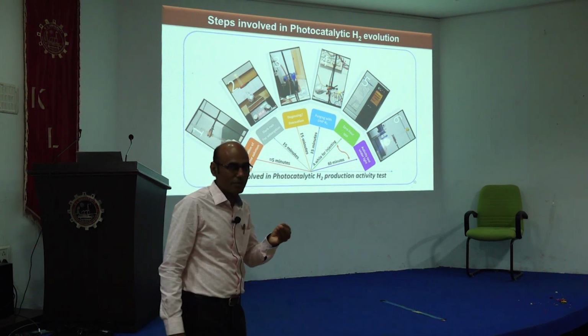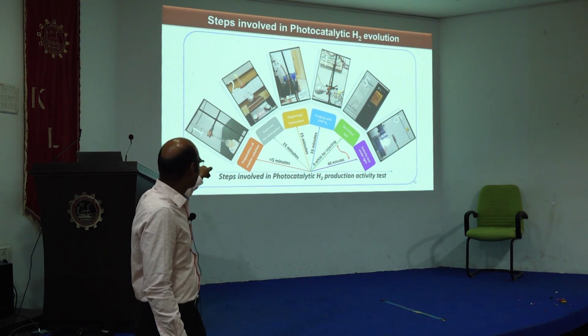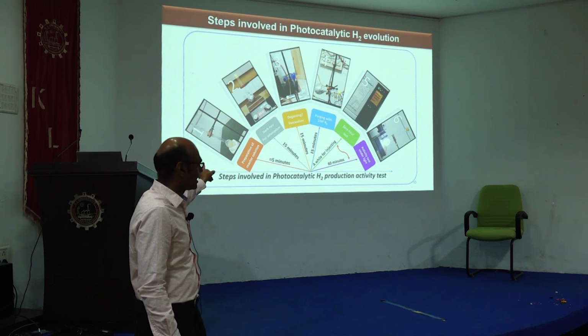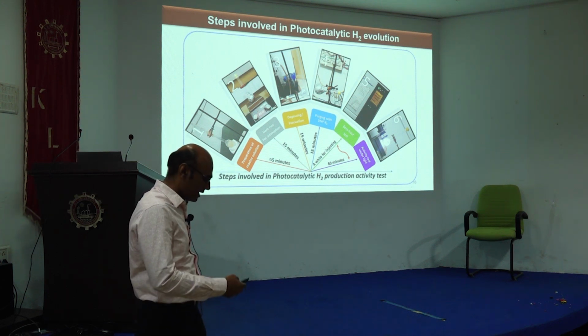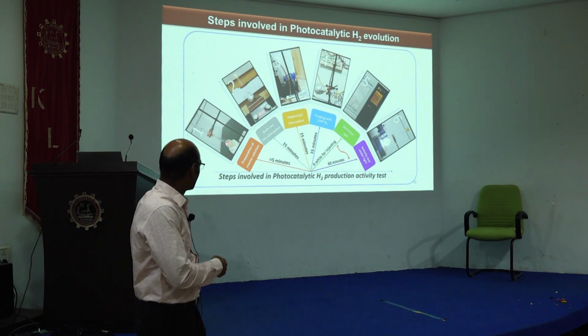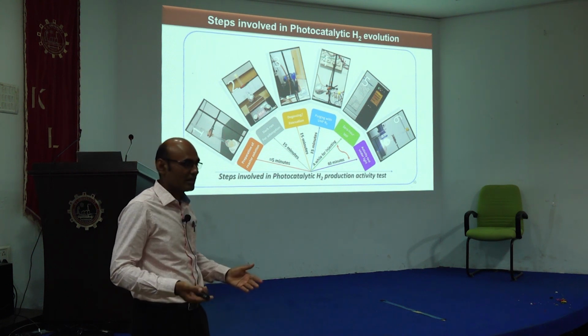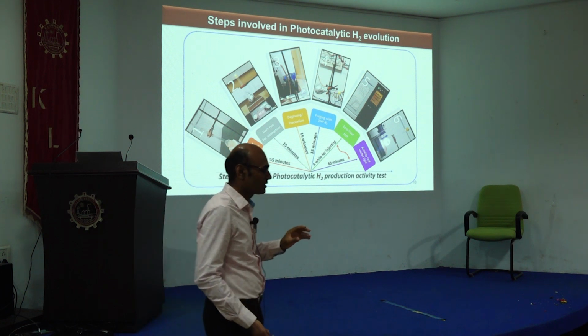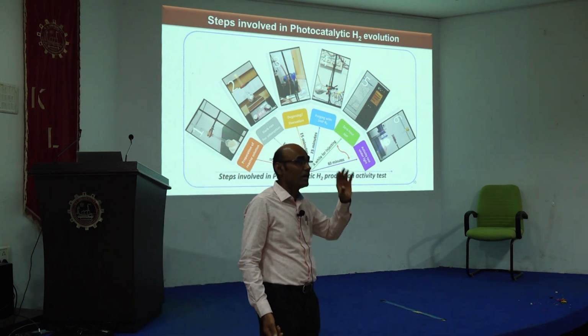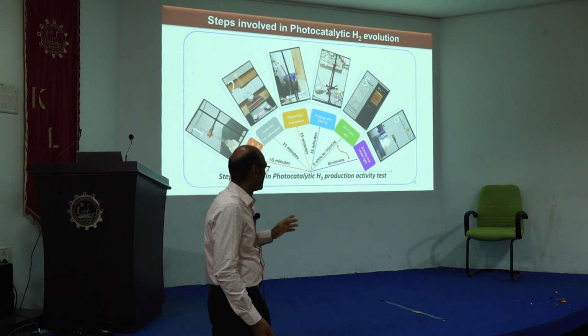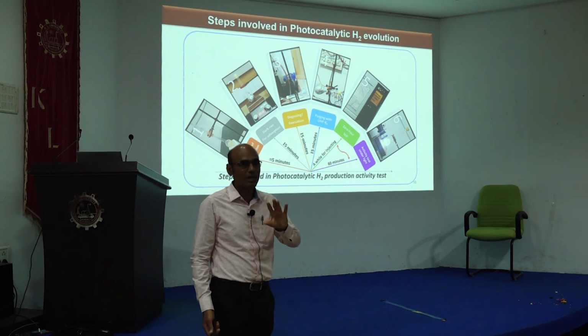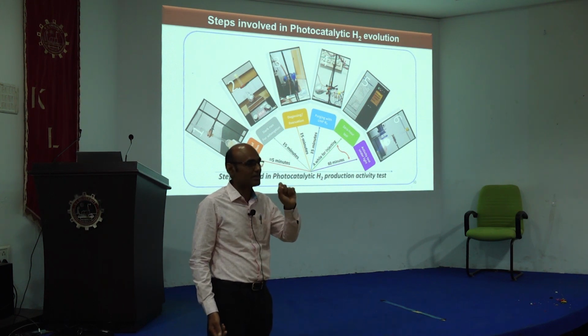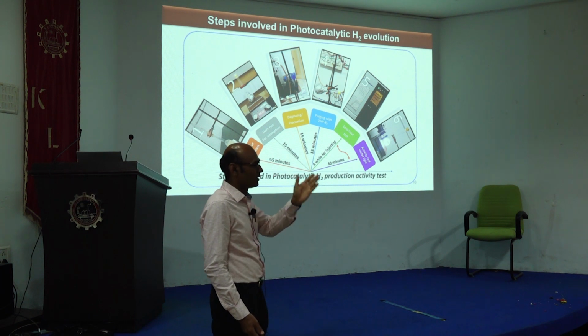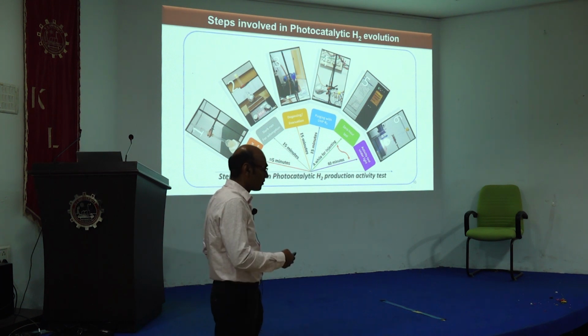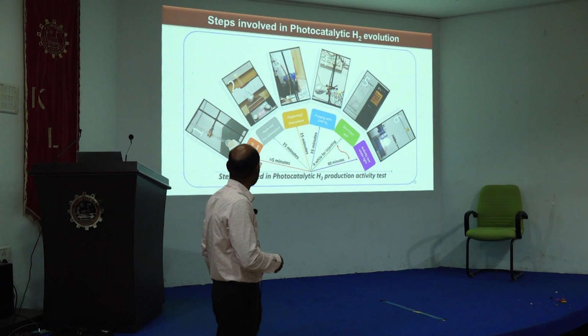First, once we prepare the material, we check hydrogen production using the reactor. This is called a quartz reactor. Quartz and glass can be used, but why quartz reactor? We want to use the UV part of the sunlight as well. Sometimes when we want to use only visible light, we use the Pyrex reactor, which will allow light absorption only above 400 nanometers.